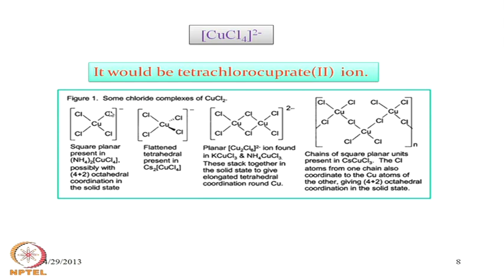So, sharing of these free end chloride groups makes one particular center an octahedral one, which is not a true octahedral one having six coordination sites or coordination number of six, but it would be considered as a 4 plus 2 octahedral coordination. 4 is from the same metal ion and 2 is coming out through sharing from the adjacent metal centers.